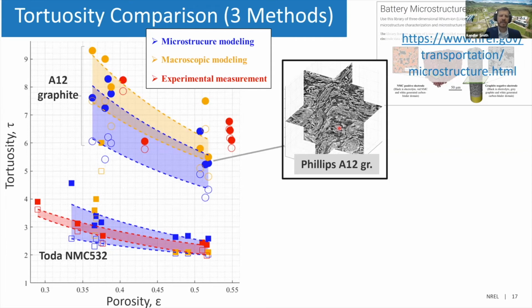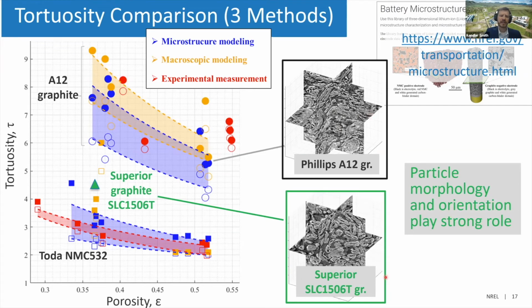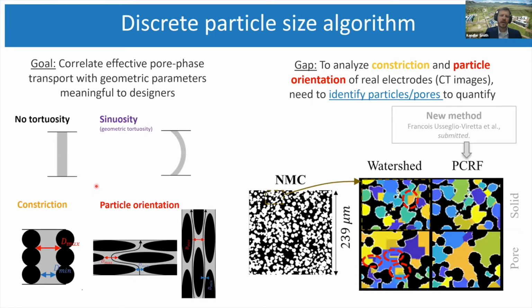For this one particular graphite, it's a platelet-like graphite, and so it has high tortuosity. There are other better graphites, such as this particular superior graphite, which has more of an ellipsoid or potato shape. It's still not quite spherical, which has a much lower tortuosity. And so particle morphology and orientation play a really strong role. In order to decouple all of this, Francois has worked with all the CT images to deduce the particle size statistics, as well as the different geometric factors which contribute to tortuosity, such as constriction of pores, where you have a smaller constricted area, as well as particle orientation.